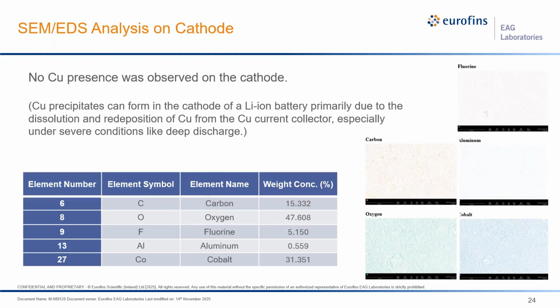And then of course, for this particular project, we need to check the compositional map, because if we are suspecting there's over discharge, then what will happen is the current collector on the anode side, which is mainly copper, will start to get dissolved, go towards the cathode and be redeposited there. Since we are analyzing the cathode now, we were looking for any sign of copper that would support the result from RGA, so that the over discharge issue would be confirmed. But here, as you can see, there is no sign of copper, which kind of eliminates the over discharge issue, because there should be copper in that case.